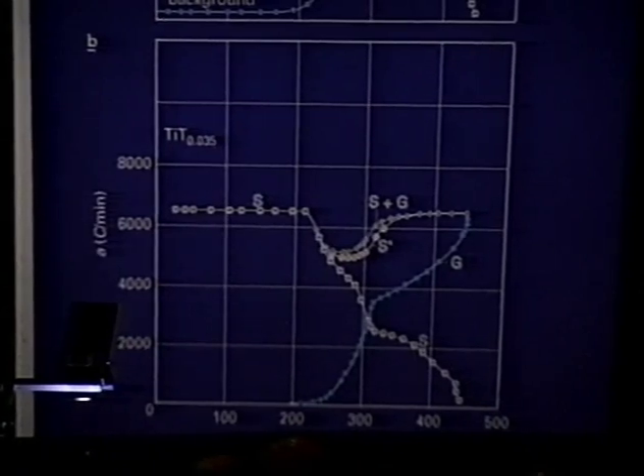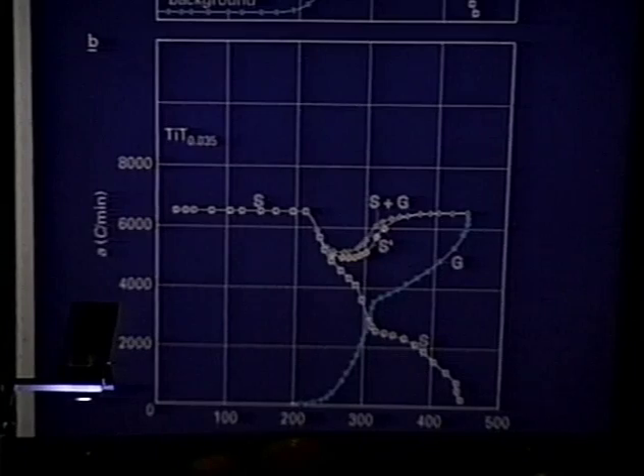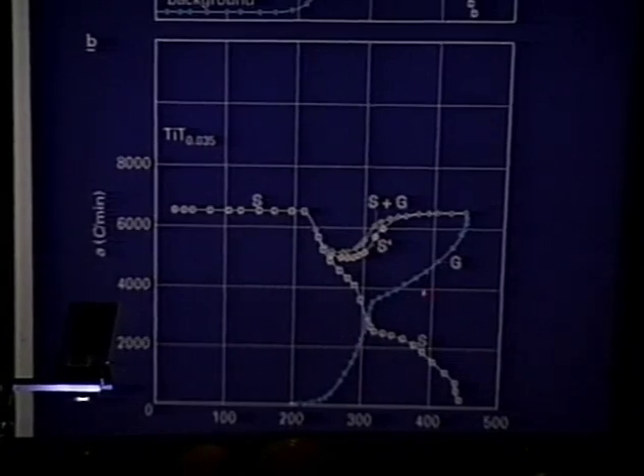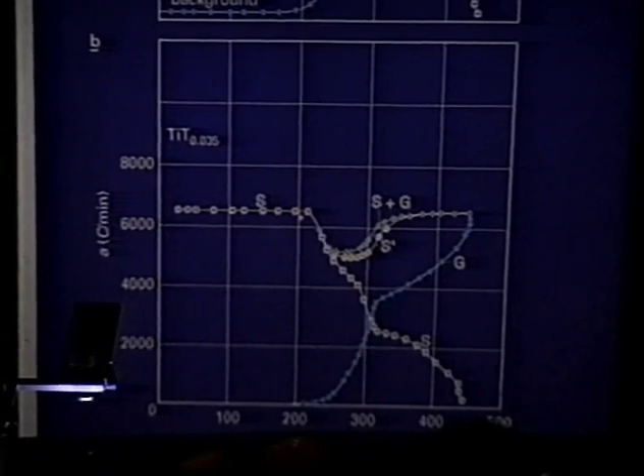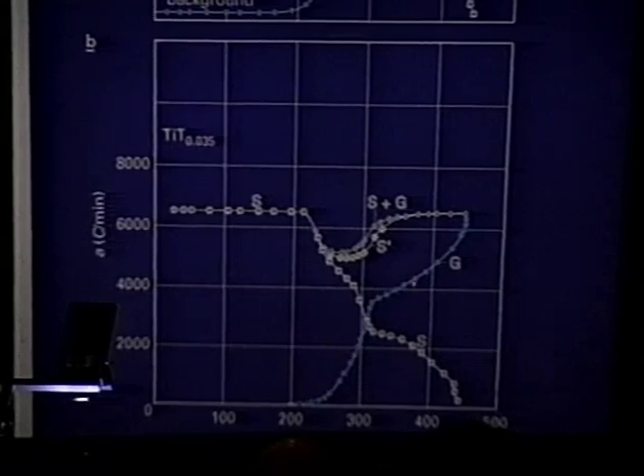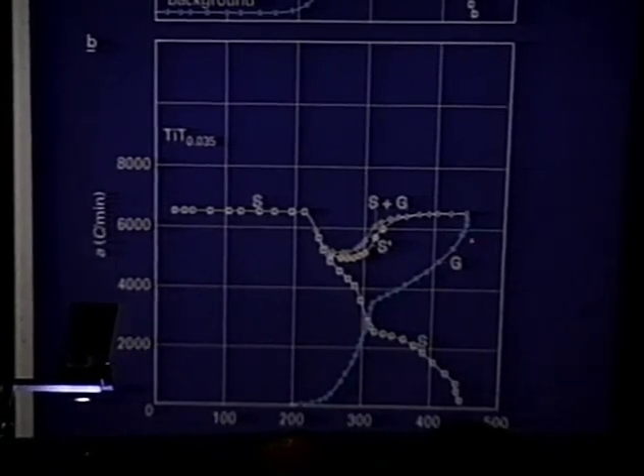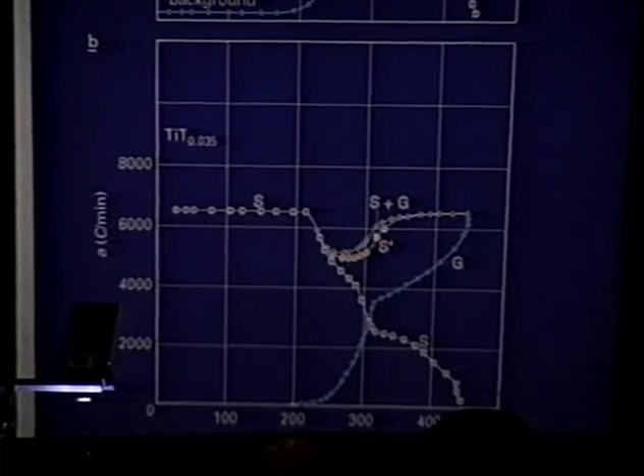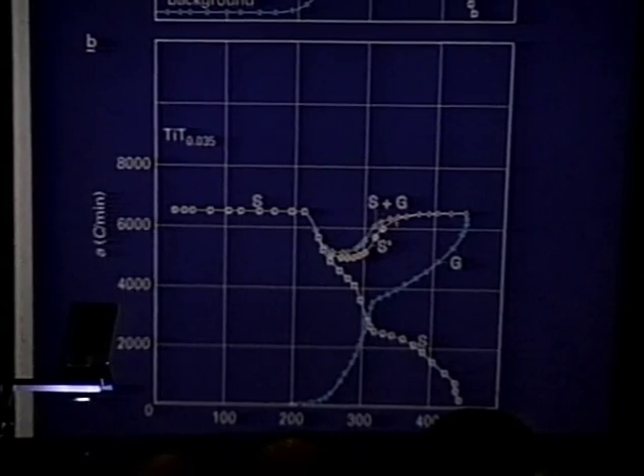We arrive to normalize the count rate of tube G to the same sensitivity as the count rate of tube S. Thus, the count rate G gives us the amount of tritium which is released from the preparation, and S plus G is a measure of the total radioactivity. We see a similar decrease and re-increase of the radioactivity as in the first experiment.